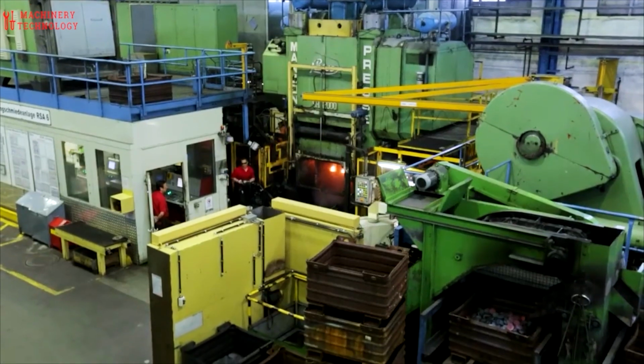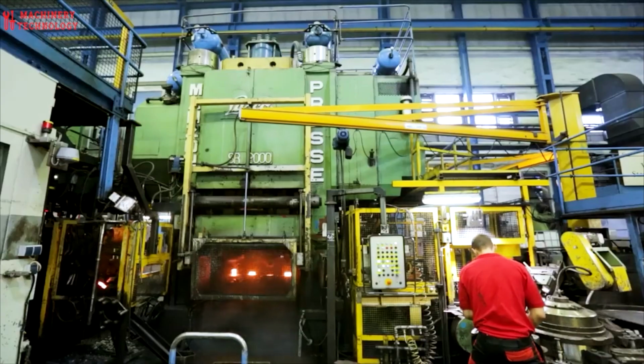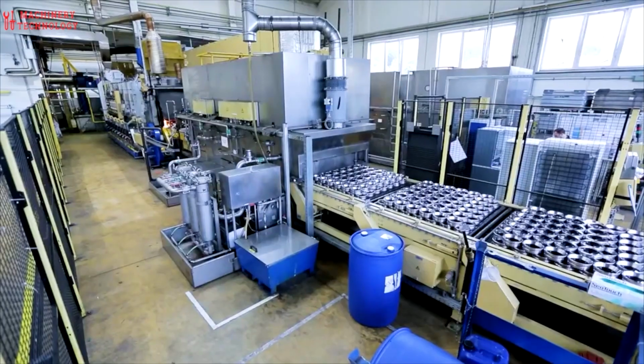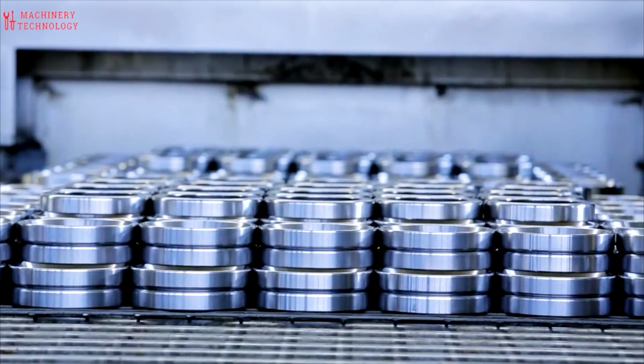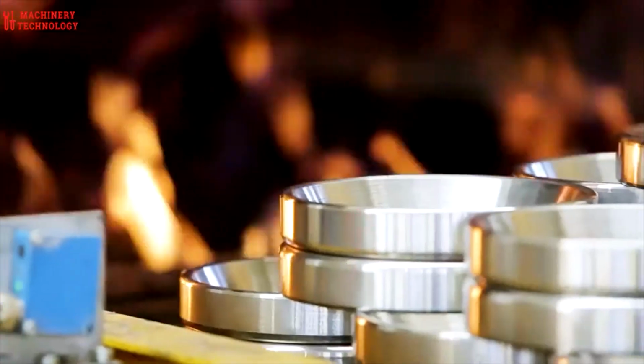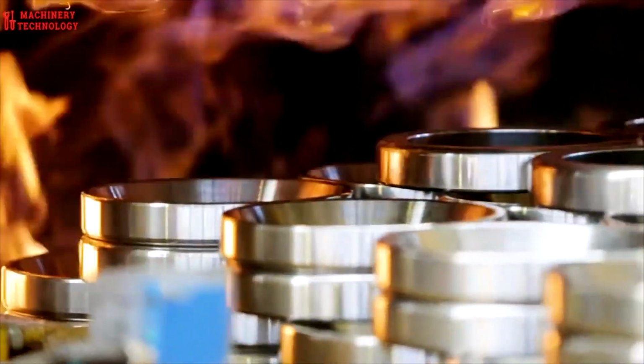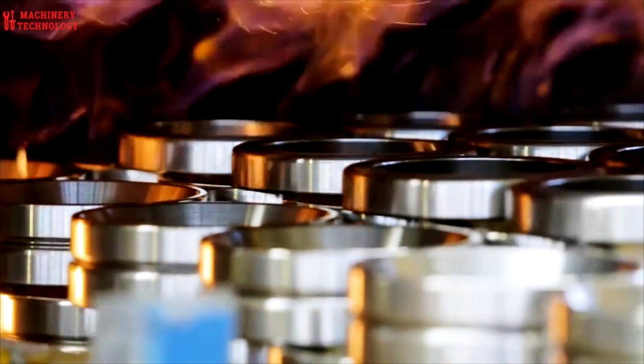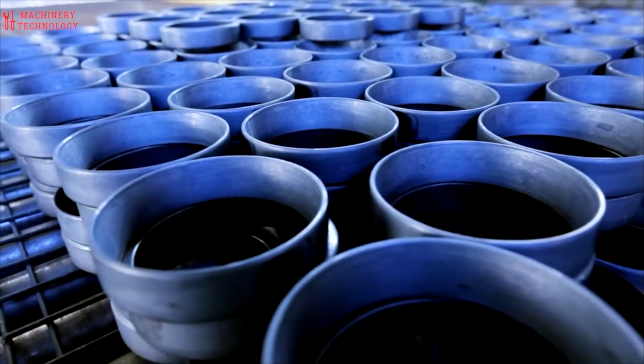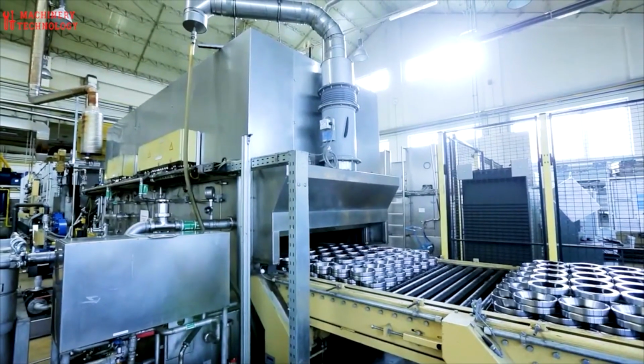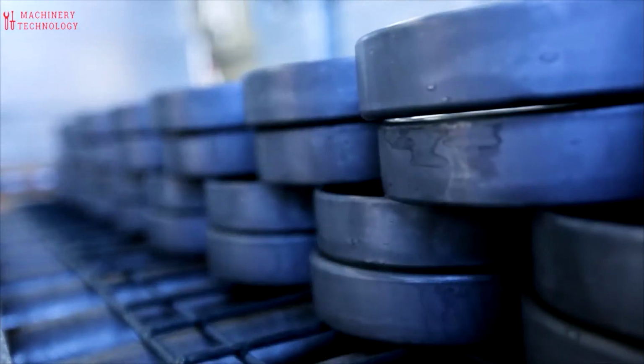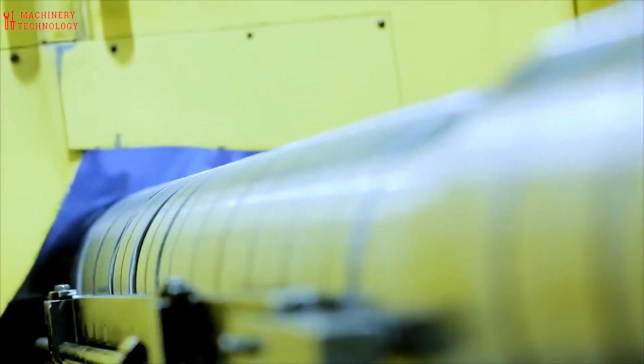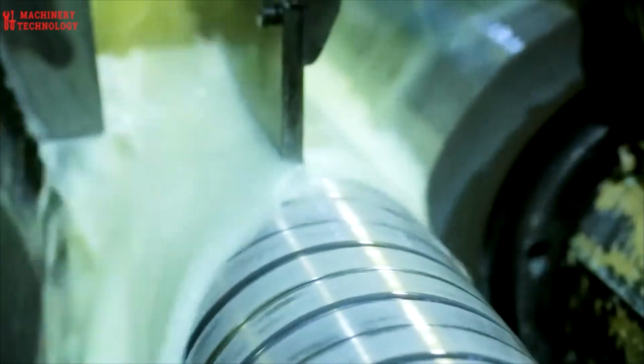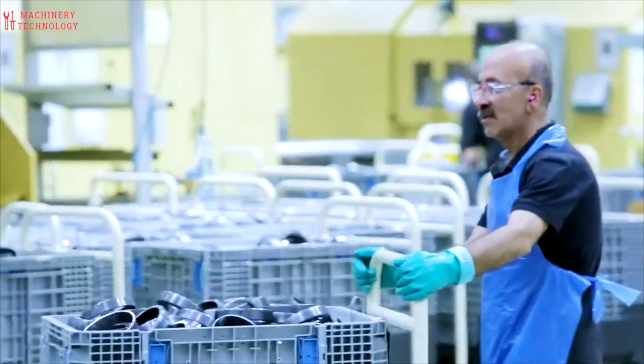The rough-cut races are put into a heat-treating furnace at about 1,550 degrees Fahrenheit, 843 degrees Celsius, for up to several hours, depending on the size of the parts. Then they are dipped into an oil bath to cool them and make them very hard. This hardening also makes them brittle, so the next step is to temper them. This is done by heating them in a second oven to about 300 degrees Fahrenheit, 148.8 degrees Celsius, and then letting them cool in air. This whole heat treatment process makes parts which are both hard and tough.